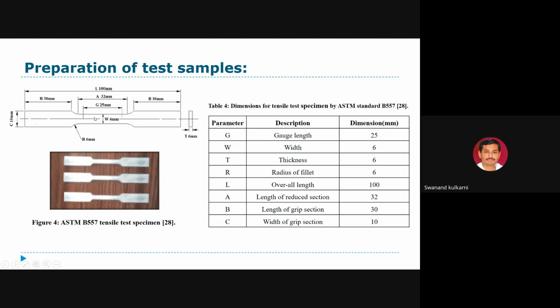And suppose in this particular case, the gauge length used was 25 mm. Then the length at the grip side, this B part is the grip side, and this is 30 mm on both sides. Then here you can see the length of reduced section. This A part is 32 mm, so 25 mm is gauge length, but this A, which is the length of reduced section, is 32 mm, and the total length, which is the overall length, is considered to be 100 mm, width is 6 mm. So here we can see the thickness is also 6 mm. So these are the standards. Here the width of the grip section is also 10 mm.